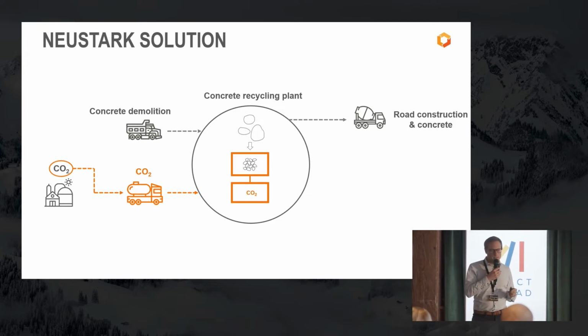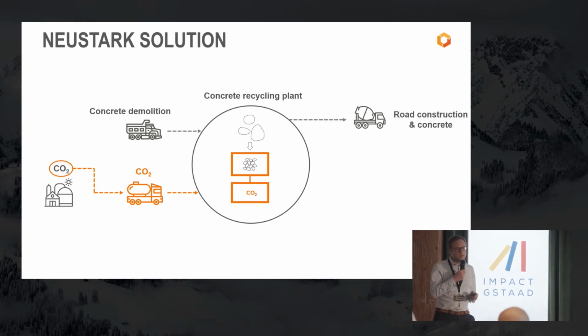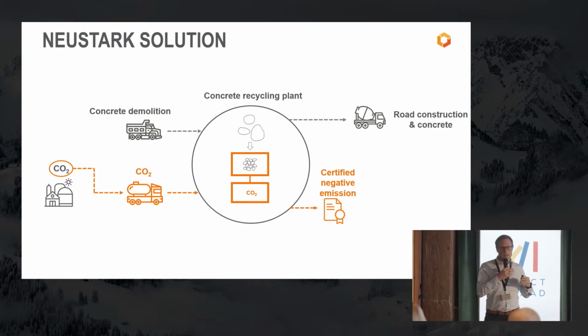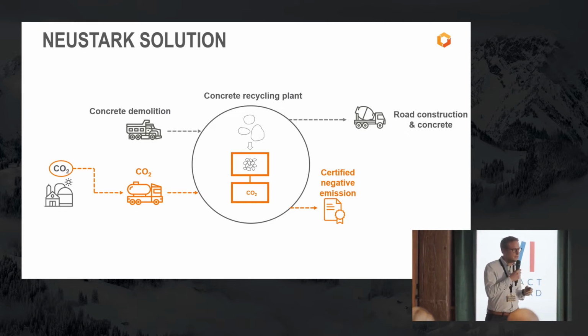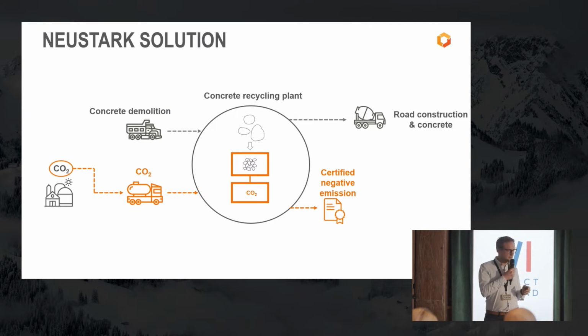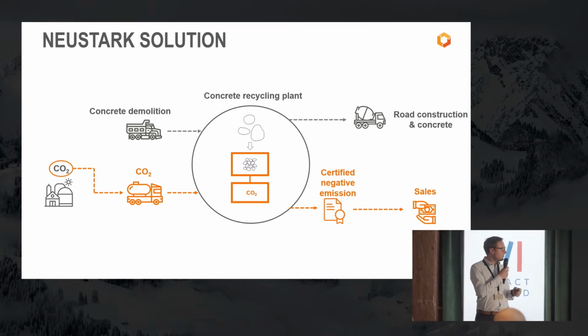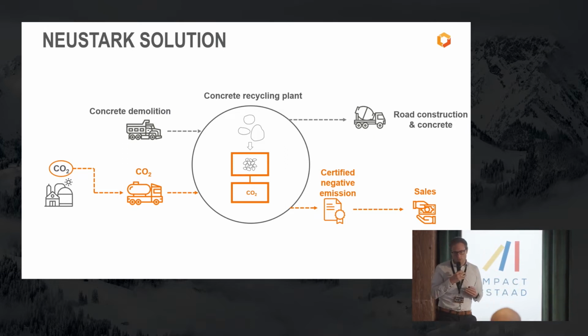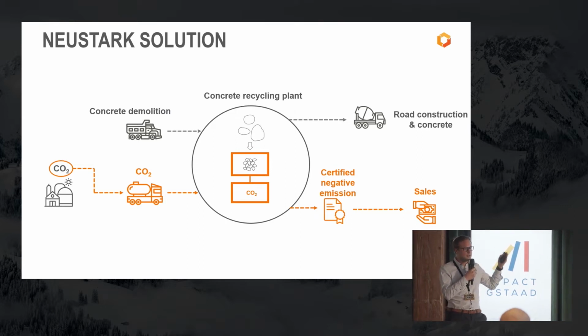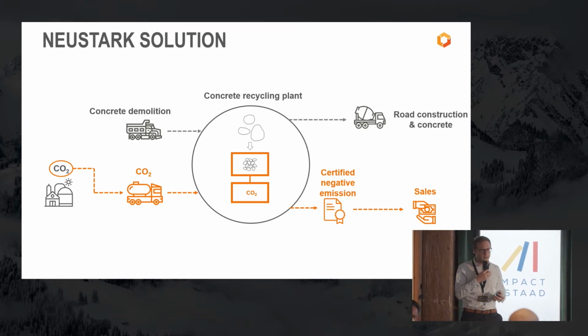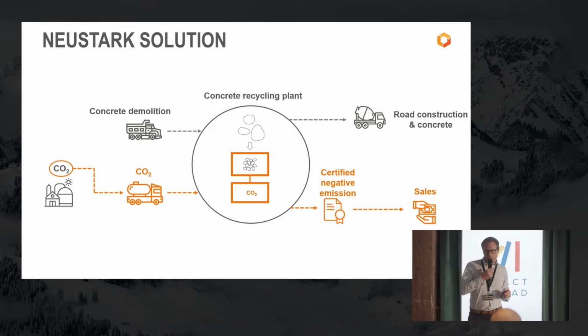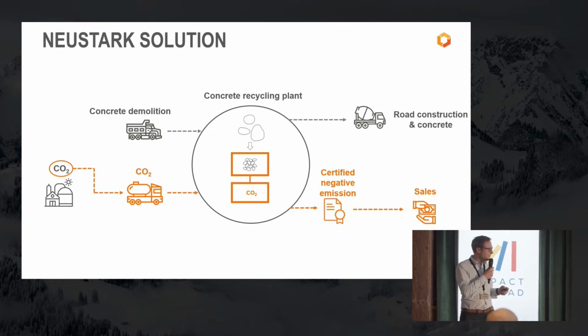In addition, we measure the environmental impact along the chain and calculate the net impact of the technology and issue so-called certificates, which indicate that we generated 1 ton of CO2 removed. And in the end, there has to be a customer for this product, which is, in our case, 1 ton of CO2 removed from the atmosphere. And the customers are usually either real estate companies which want to purchase concrete with a lower footprint, or corporations which have a very high climate ambition towards reducing greenhouse gas emissions.